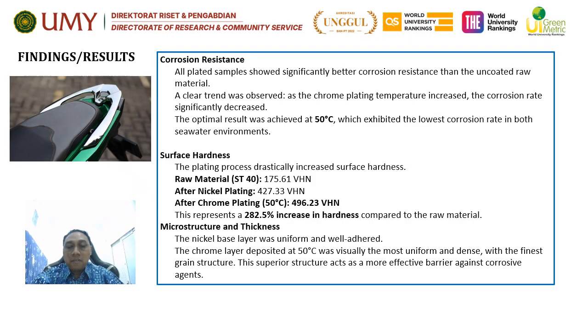The result of this research is the corrosion resistance. All plated samples showed significantly better corrosion resistance than the uncoated raw material. A clear trend was observed as the chrome plating temperature increased: the corrosion rate significantly decreased. The optimal result was achieved at 50 degrees Celsius, which exhibited the lowest corrosion rate in both seawater environments.